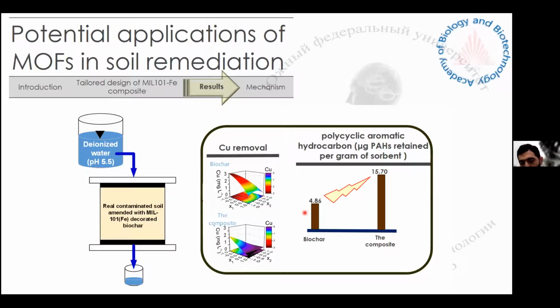Here you can see that 1 gram of the biochar almost removed 5 microgram of the polycyclic aromatic hydrocarbon. And I should explain that this is not a removal, it's like a retention. So this solution that we collect had less polycyclic aromatic hydrocarbon, and it means that the biochar fixed the leaching of these polycyclic aromatic hydrocarbon from the column. But once we had a composite, it got better performance, and we had a 3 times improvement in retaining the polycyclic aromatic hydrocarbon compared to the biochar. So the composite just justified its usage inside the soil.